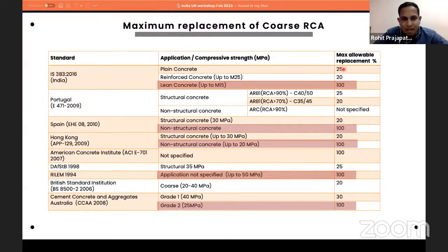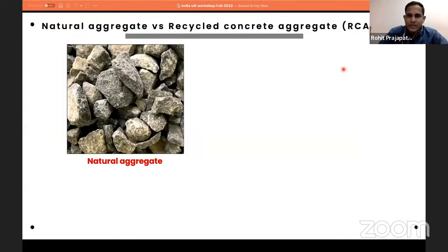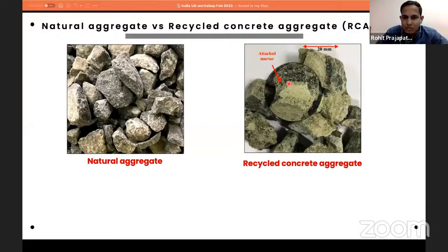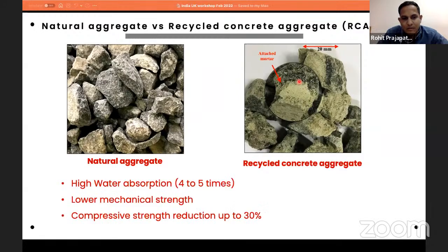properties of recycled aggregates. So what is the basic difference between natural aggregates and recycled aggregates? We have attached mortar on the surface of the aggregate. This attached mortar is responsible for high water absorption, which could be 4 to 5 times higher, and lower mechanical strength. And if you replace natural aggregate with recycled aggregate, the strength could reduce by up to 30%, and there could be other serious problems related to durability as well.